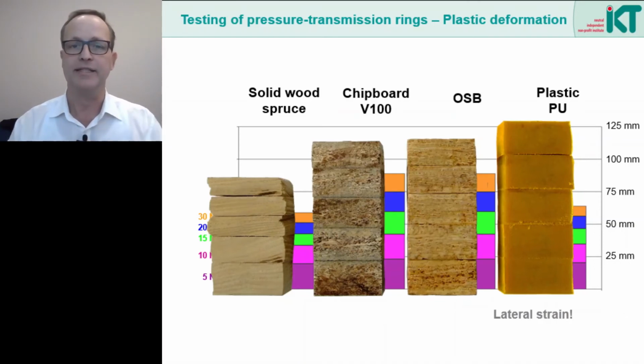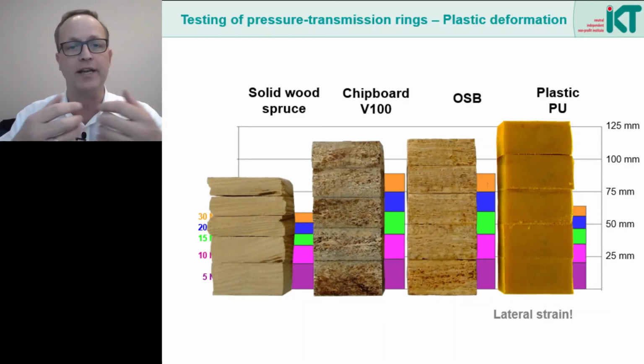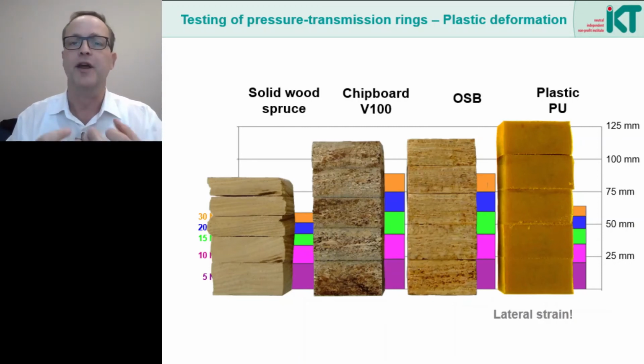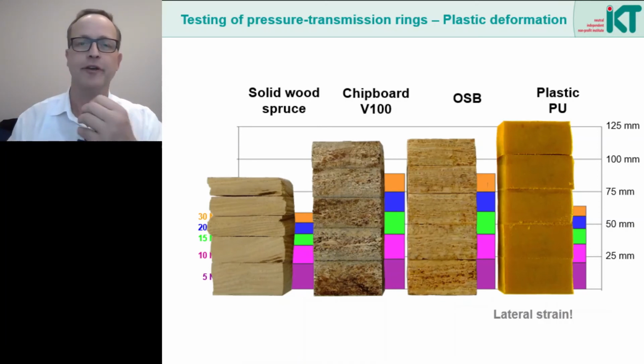In all cases, the wood also deforms plastically. This also means that the wood adapts well to the concrete surface. In addition, wood has a low transverse elongation, so low lateral strains, which means that there are only small splitting tensile forces in the concrete. The plastic far right, on the other hand, is comparatively elastic. All test specimens have returned to their original geometry after being unloaded. However, the lateral strains of plastic are significantly higher.